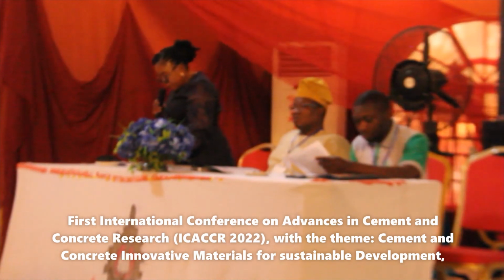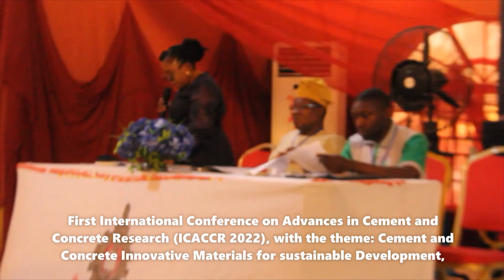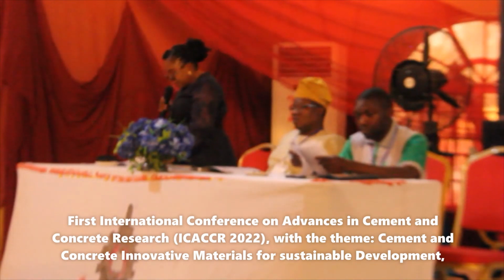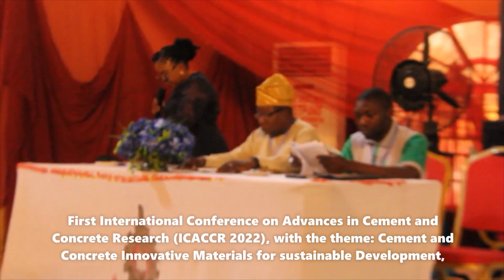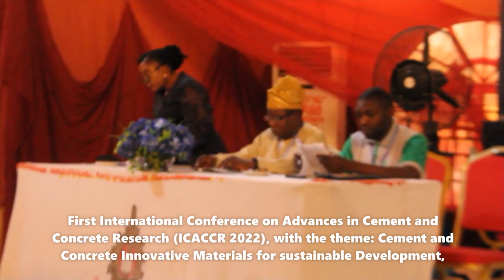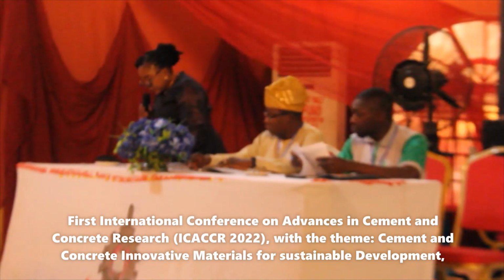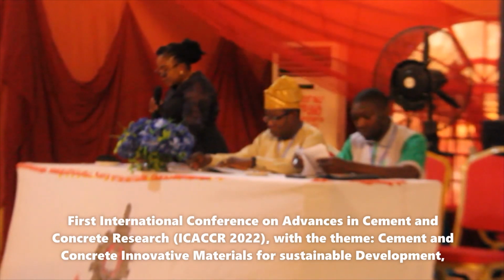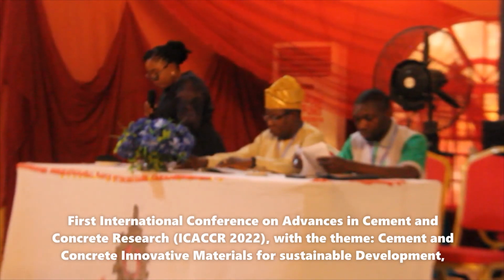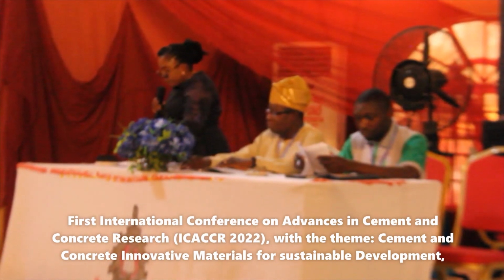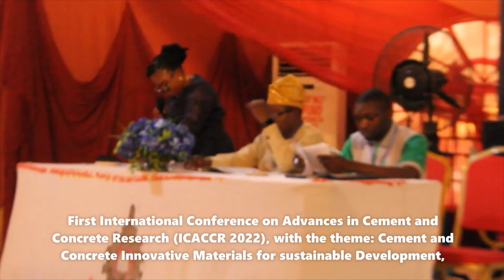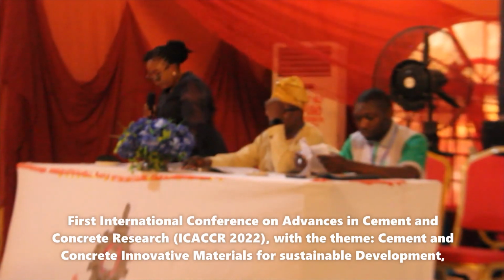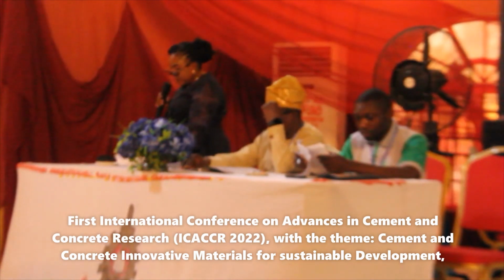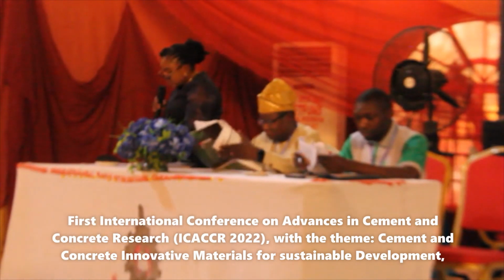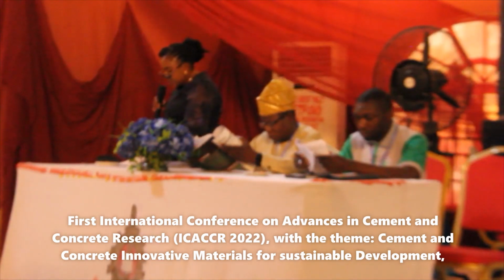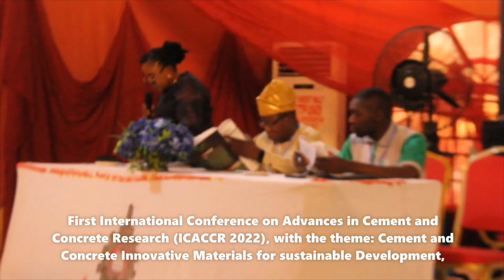The fourth paper was presented by Mr. Oyejobi: performance of blended cement containing fly ash and copper slag. From his findings, he said that the blended cement with 30% replacement is applicable for major structural work, while that of 50% replacement can be used for plain work. In conclusion, he said that the blended cement has higher strength. It is used to conserve our natural resources, as it reduces pollution and preserves the environment.